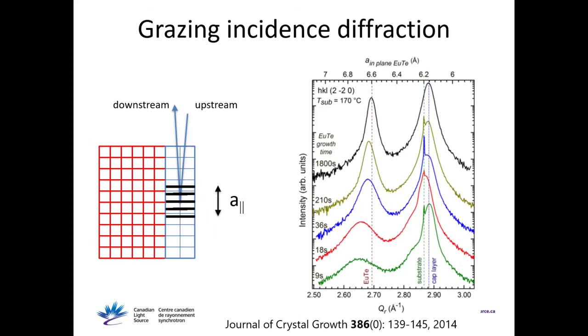When we go to the in-plane geometry, choosing an HKL set of planes completely in the plane of the sample — which is very grazing — the measurement changes completely. All of a sudden we can see the peak from the europium telluride nanodots, with the signal from the cap layer and a little from the substrate. We have good signal and can clearly see peaks from those 40 ångström-thick nanocrystals. We can see the peak changes position and width with growth time, and can start drawing conclusions about strain and lattice parameter.